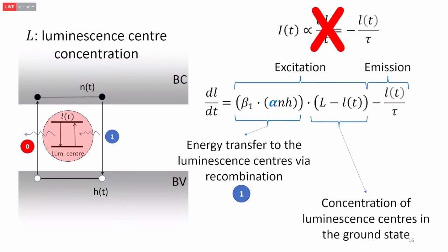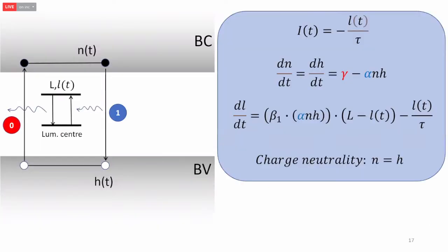And the second term is actually the concentration of available luminescence centers in the material, because we are working with a system that has a limited concentration of luminescence center. This is what happens in the nature. Depending on the dose in the material, can saturate all the luminescence center, and then there is no way on putting more dose, because you already saturate, you're not getting any light out unless you increase the concentration of luminescence center. So it's a limiting, so it's an important factor here.